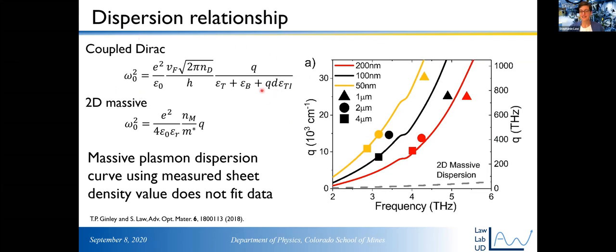What I want to emphasize is that there are no fitting parameters. We didn't use a single fitting parameter. These are all constants. We know the sheet density. We can measure this with Hall effect measurements. This is the permittivity of air, which is just one. This is the permittivity of the sapphire substrate, which we know. And this is the bulk permittivity of bismuth selenide, which we also know. Film thickness and wave vector, we know. There are no fitting parameters here. And you can see that our experimental data matches the theory really quite well.